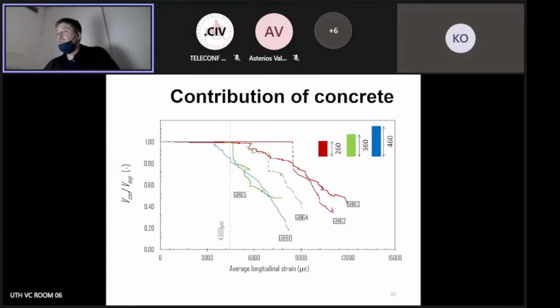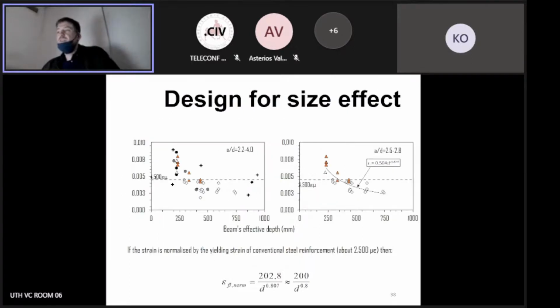And here what we have is the experimental contribution of concrete against the longitudinal strain. And this also was very interesting to see that when we increase the size of the element, the decrease in the contribution is steeper, and this made me think, why not reflect back on these design equations from the late 90s and try to improve them a little bit to account for this effect.